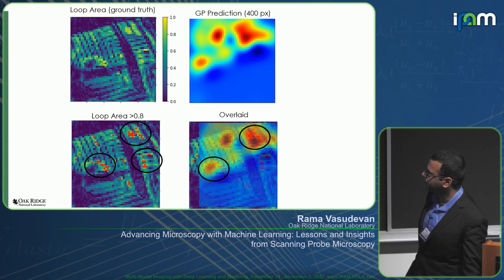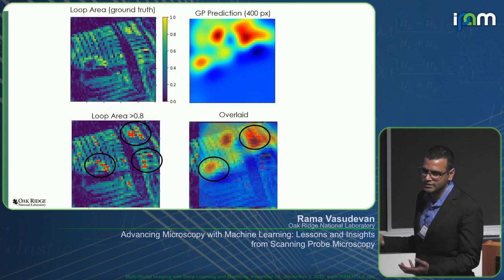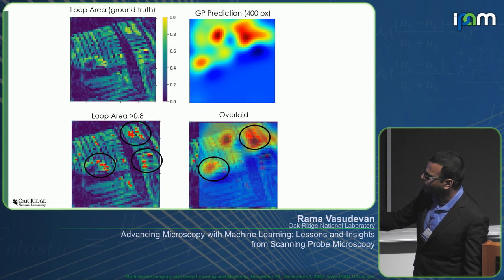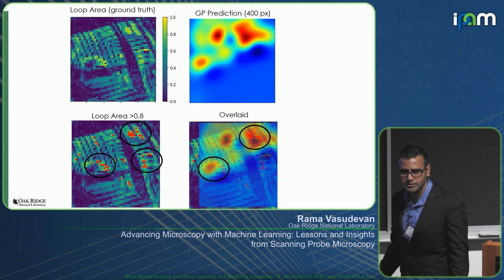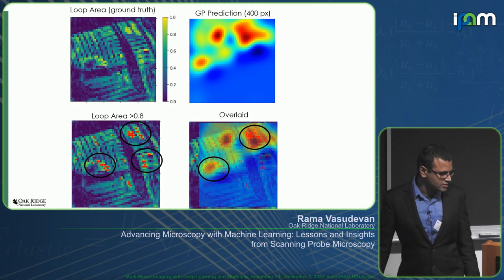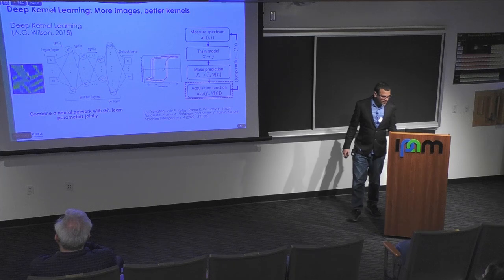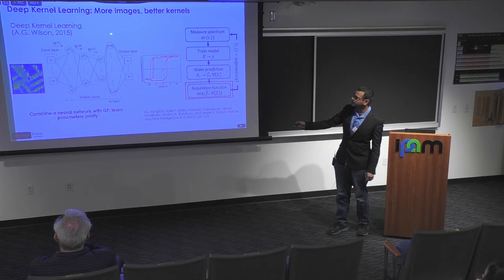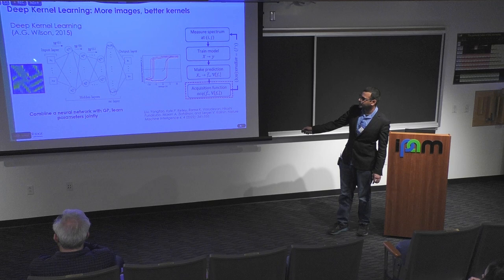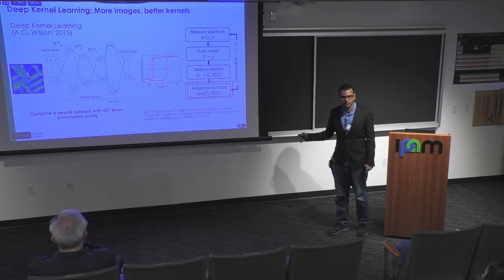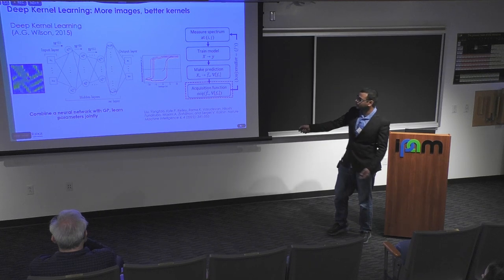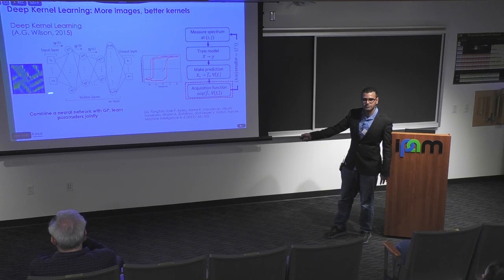The reason we're not capturing any of the image structure is because the kernels that we are using in our Gaussian processes are basically RBF kernels or Matern kernels. It doesn't really matter, but they are insufficient to describe the kinds of hierarchical domain structures that we observe in ferroelectric materials. The answer to that is something called deep kernel learning, proposed by Andrew Gordon Wilson in 2015. In deep kernel learning, instead of using a kernel like an RBF kernel with a single parameter, you use things like convolutional neural nets with learnable parameters for that kernel.